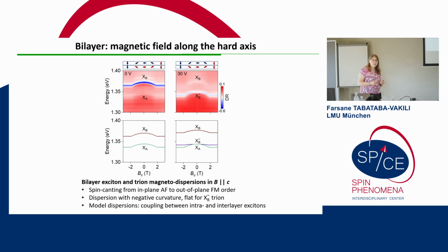Now, let's apply a magnetic field, starting with the out-of-plane c-axis. Here we observe this gradual spin canting with the parabolic shift in exciton energy. And we see this for XA, for XB, and also for XB minus, although the dispersion is a bit flatter for the trion.